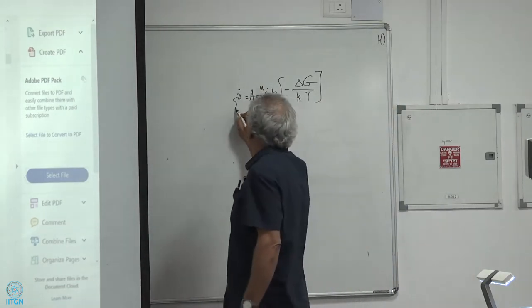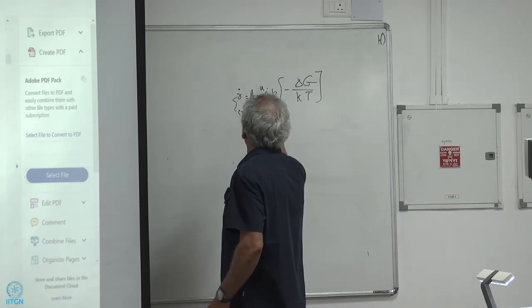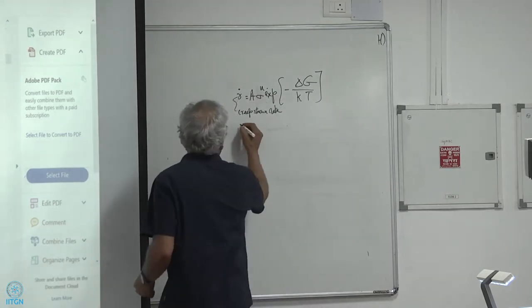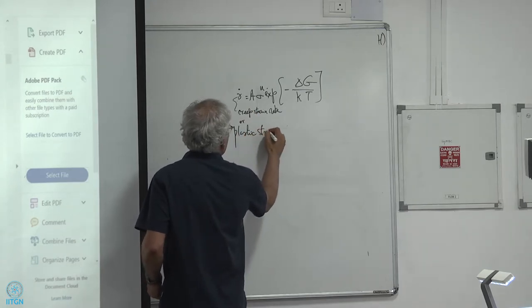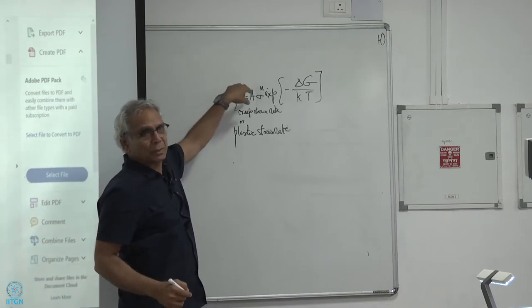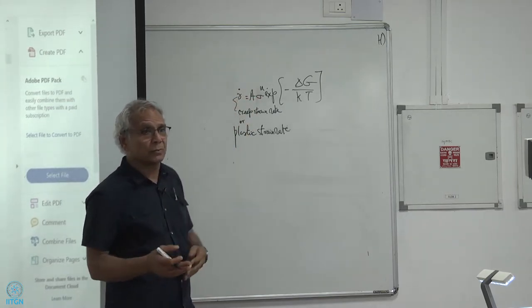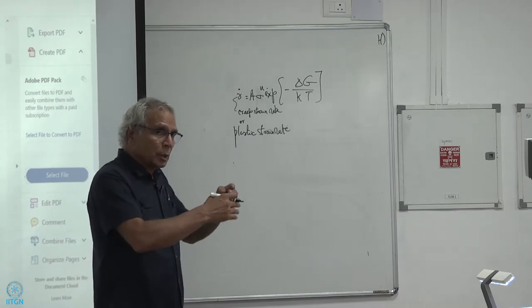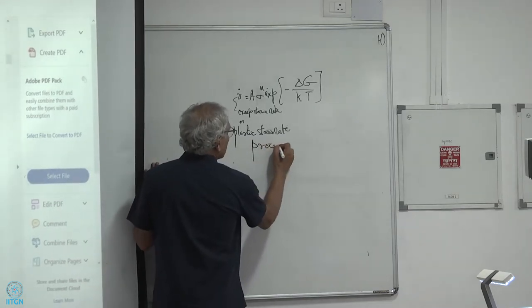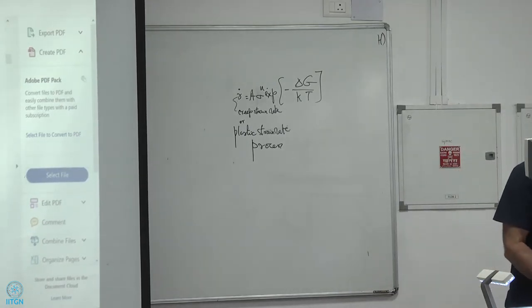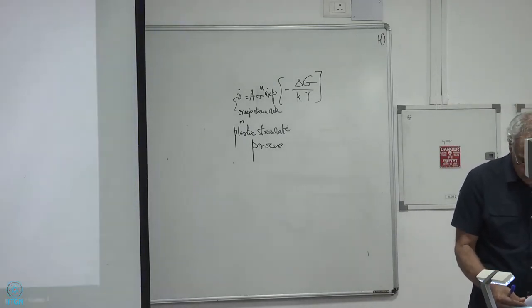So here come the dislocation theories a lot. A lot of dislocation theory goes in here, but I'm just giving you the final result. So you now remember the prism planes and the pyramid plane. So here is a soft grain, and here is a hard grain. If you have a pile up here and you want to transfer the slip to the next grain, and the next grain is oriented as a hard grain, that means it's hard to slip in there.